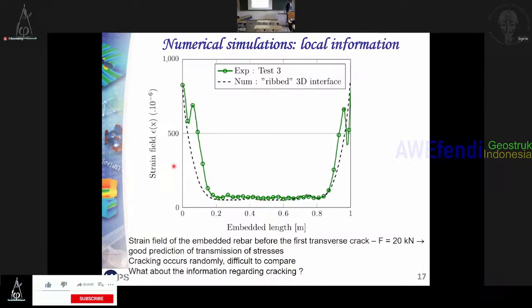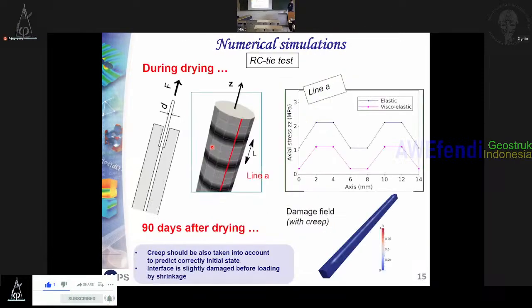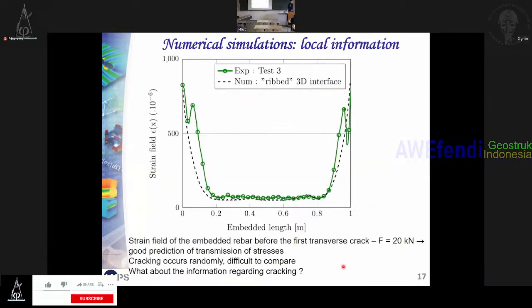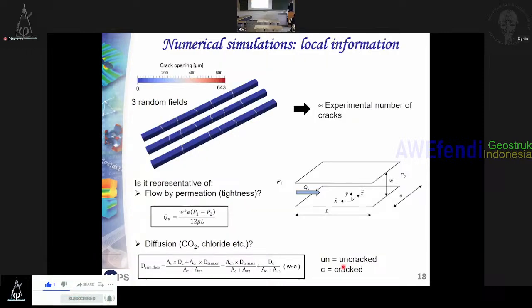If you look at local information, that was the objective of my talk, you can see here that you are also able to predict the evolution of the strain along the rebar. But here you can see that you have this jump, so we already have a crack. If you remember, what we have predicted is not a complete crack, but only some damage at the interface. So it's not completely perfect, but we already have some damage because of drying.